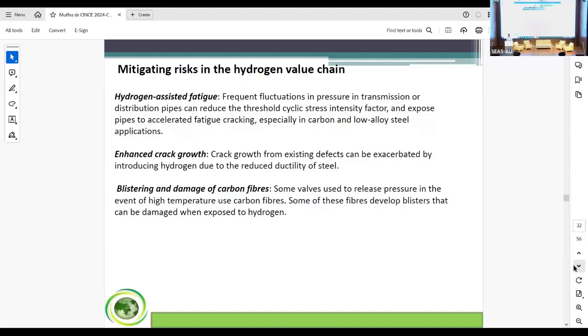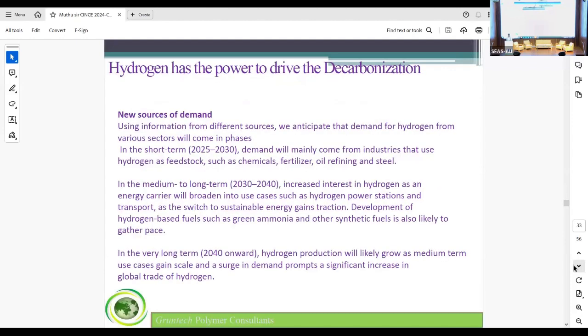This is another very important point. So, some valves used to release pressure in the event of high temperature use carbon fibers. Some of these fibers develop blisters that can be damaged when exposed to hydrogen. So this point you have to keep in mind when you deal with carbon fibers.